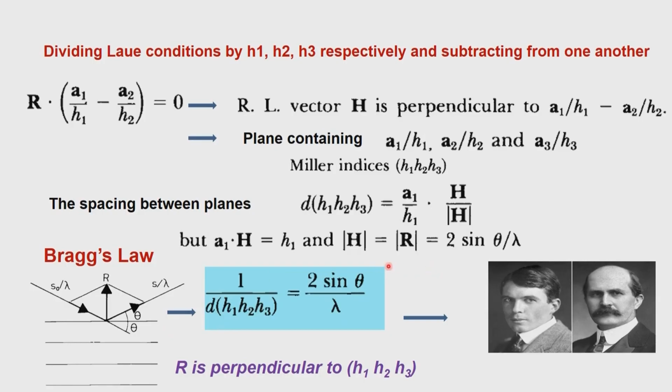So, we can get solutions to A star, B star, C star, the values of the reciprocal lattice, directly from this expression. Once we have the reciprocal lattice information, we can convert it into the direct space information. So, the geometry of the unit cell and its a, b, c, alpha, beta, gamma values and the corresponding spacing of the planes inside the crystal, we will be able to get both using this equation. So, the entire geometry of scattering can be obtained.